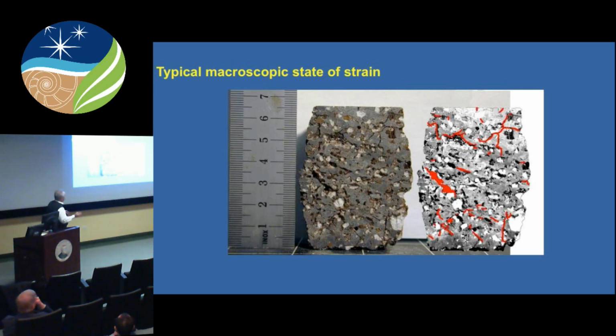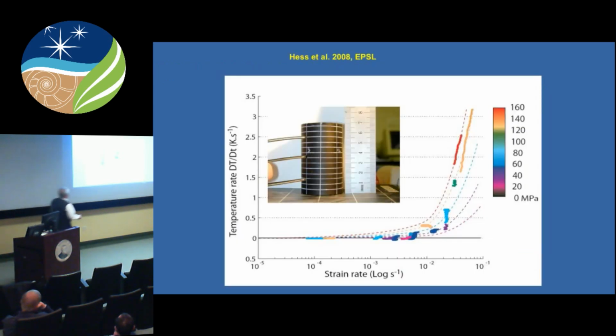And you see what looks like a very violent thing here, 3 thermocouples which have been placed into drill holes. And we simply deform these things at variable strain rate and look for the onset of viscous heating. We do it with real rocks as well. Of course, with real rocks we have heterogeneity, and you can look at these samples and decide for yourself the degree to which you think we have achieved homogeneous deformation versus heterogeneous deformation.